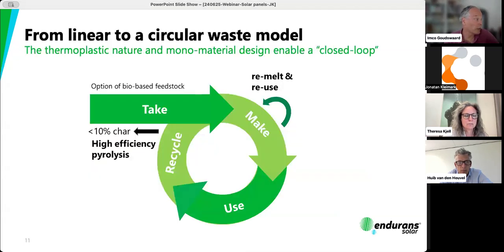And an additional benefit is circularity. By using these polyolefins and just one material in your stack, we can almost close the loop. Polyolefins are known for pyrolysis, so thermal degradation at high temperatures without oxygen, where you can break down the polymer to its monomers again, and these monomers can be used to polymerize new resins again. And that efficiency is quite high, almost 90%. So the other 10%, that is where you don't close the loop yet. But of course, there's also improvement in the technology.